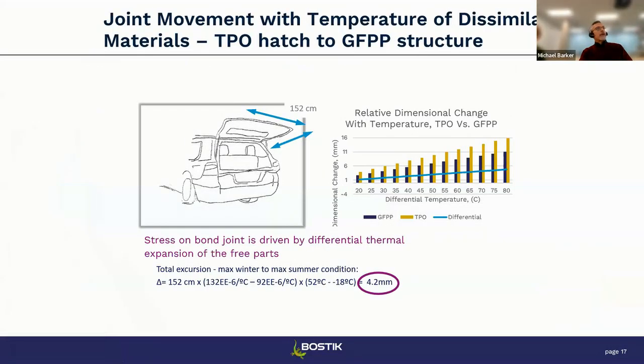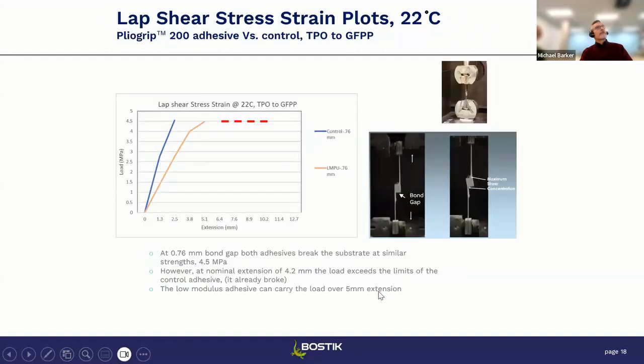So we put together an example. And in this case, we're using an example of a TPO bonded to a glass-filled tailgate for an SUV. And we used the dimensions 152 centimeters square. And we ran that through a basic engineering program or equation using extreme temperatures, cold versus hot. And we determined that those two substrates, when the temperature varies over the range given, can vary up to 4.2 millimeters. Now, if you hold your fingers up and say, well, gosh, 4.2 millimeters isn't very much, or is it? So that's a number that we're going to play with right there, that 4.2 millimeters.